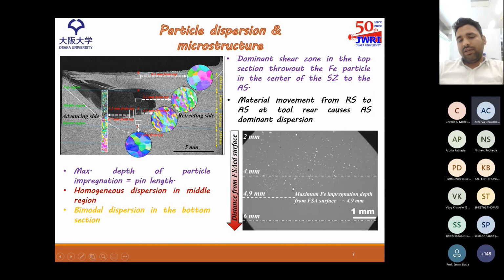Okay, so interestingly, we have observed that the particles can be impregnated up to 4.9 millimeter depth. The last particle which is impregnated is at 4.9 millimeter. And luckily we have a pin length of also around 5 millimeters. So we can see the first benefit, that the particle impregnation depth can be controlled by the pin height, which is achieved here, and the particles are impregnated up to the pin height only. And there's a homogeneous dispersion in the middle and a bimodal distribution in the bottom section, as explained earlier.